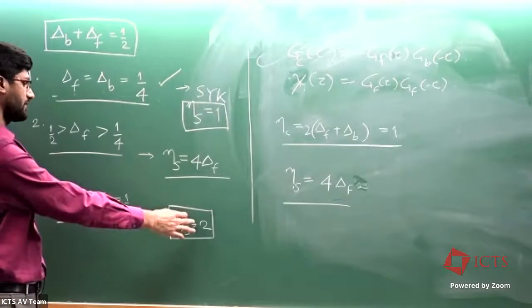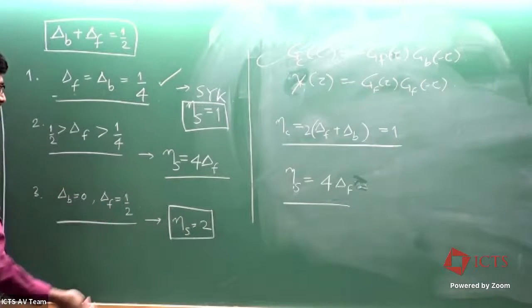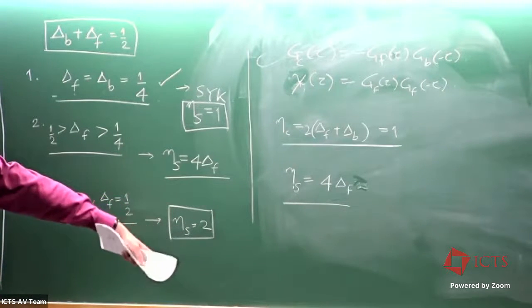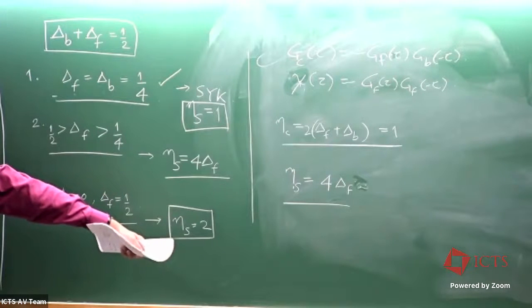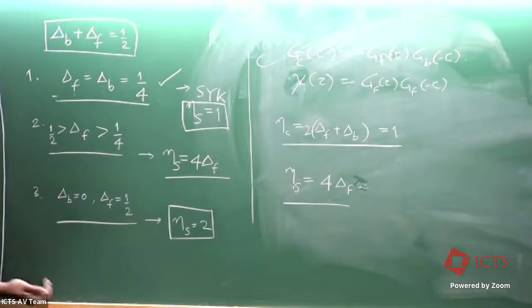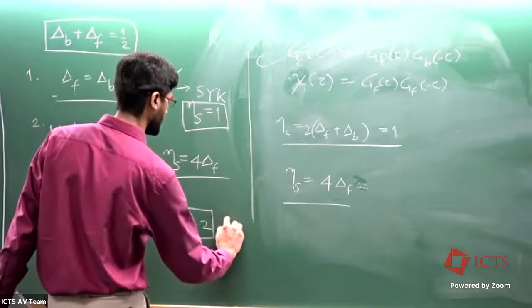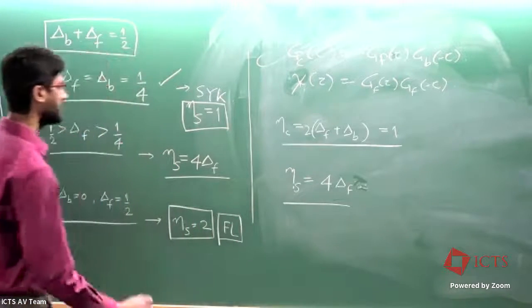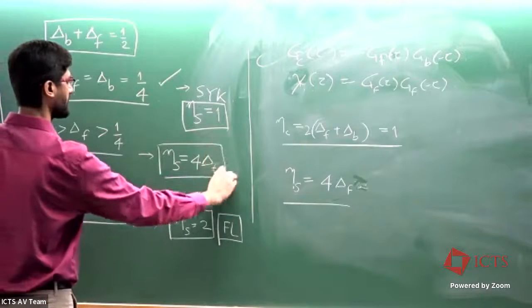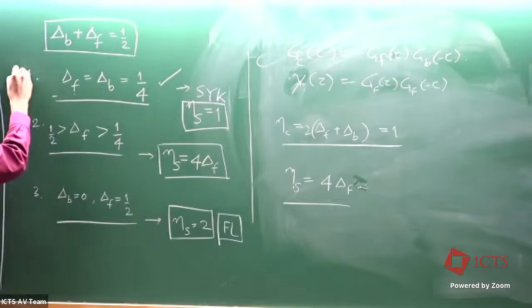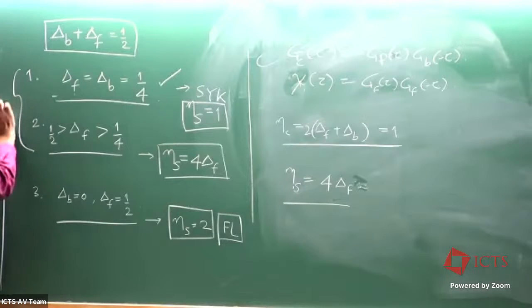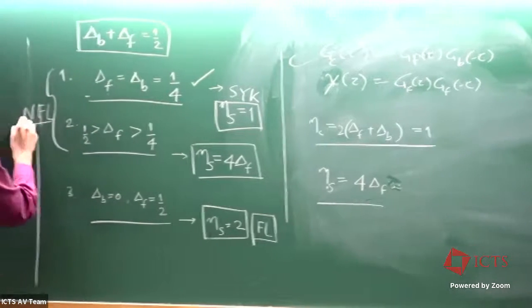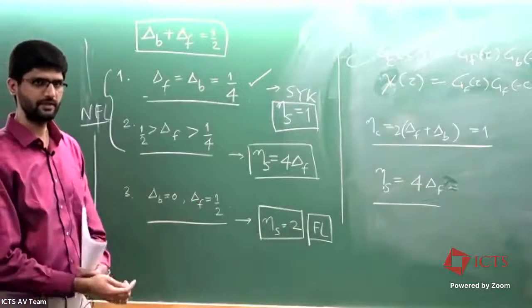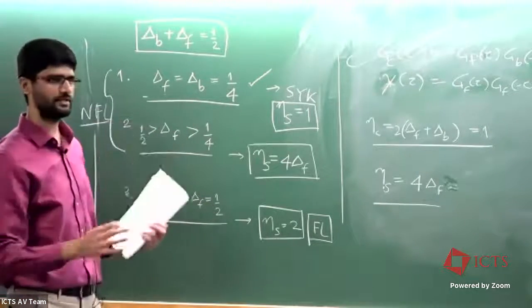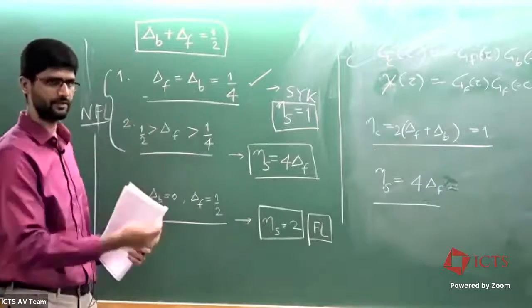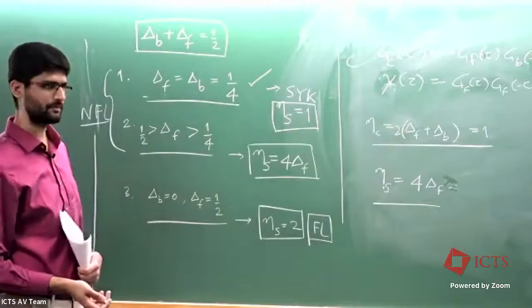So if you recall, this is actually Fermi-liquid-like. This gives you a spin-spin correlator which is 1/tau squared in imaginary time. So this solution corresponds to a Fermi-liquid-like phase, whereas these two solutions are your critical solutions. Both of these solutions are non-Fermi-liquids, and this one is a Fermi-liquid solution. So now we have looked at the general model. We have found that there are three possible solutions of this model.